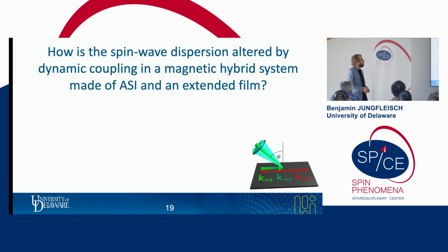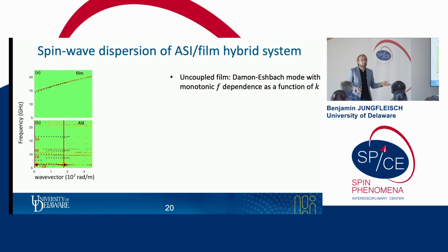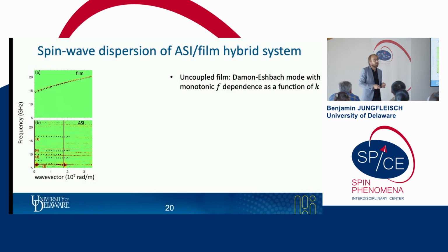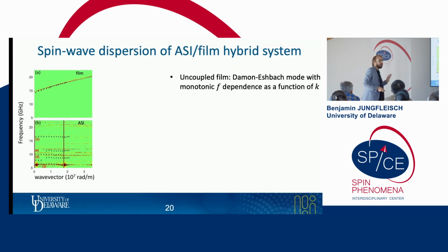So how is the spin wave dispersion now altered by this dynamic mode coupling in the hybrid system? Again, I want to explain first how to read this data. In this case, the color code represents the results of the dynamic micromagnetic simulations. The symbols represent the results of the wave vector resolved BLS measurements. And in this case here for the film, we also fit the experimental data with the Kalinikos-Slavin model. So this is just the Damon-Eshbach mode. So for the uncoupled film, we just see the Damon-Eshbach mode, monotonic increase of frequency with wave vector.